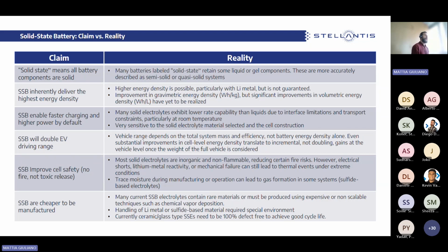In terms of driving range, the vehicle driving range doesn't depend only on the energy density of the cell alone, but it depends on the total system mass and efficiency. So even with a substantial improvement at cell level, the real impact at the vehicle level is, from the practical point of view, quite reduced. In terms of safety, we have to bear in mind that most of the solid electrolytes are inorganic and not flammable, reducing the fire risk. However, electrical short, lithium metal reactivity, and mechanical failure can still lead to thermal events under specific conditions.